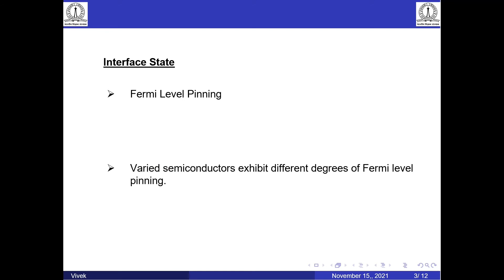Let's discuss interface states. In reality, regardless of the work function values, charged interface states can pin the Fermi level at a given energy value, altering the barrier height for both carriers — a phenomenon known as Fermi level pinning. In contrast to the Schottky-Mott rule, the barrier height generally exhibits minimal dependency on the value of the semiconductor or metal work functions.